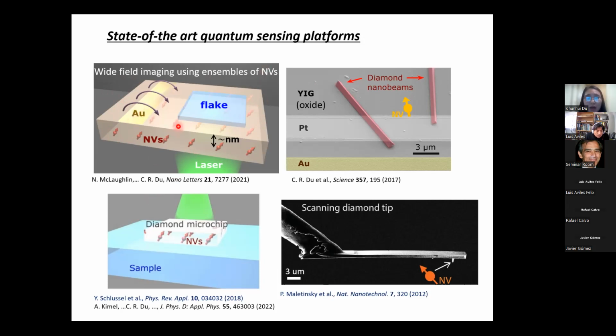So in this case, we can implant the NV center a few nanometers below the diamond surface. And then we can transfer the material, for instance, nanoflake, or grow the material directly on diamond, and then using ensembles of NV center to achieve a wide field, we can detect the photoluminescence using a camera, and so we can get a wide field imaging of NV center ensembles and use that to study the local properties of the material. So sometimes the material cannot be directly grown on diamond. For instance, complex oxide material may require a lattice match substrate for the epitaxial growth. So in this case, we can pattern diamond nanostructure containing NV center and transfer it on the material surface.